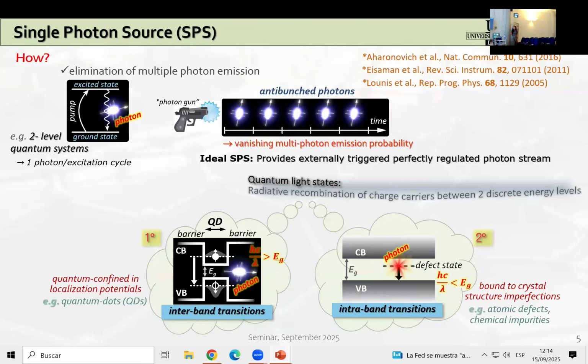Now, these systems can be made in such a way that the recombining charges are either quantum confined in localized potentials, like in quantum dots, for example, or they can be bound to imperfections within the crystal lattice. Like, for example, we are talking about atomic defects here or chemical impurities. So in both ways, per excitation cycle, there will be emission of a single photon, and the energy of this photon will depend on the system. So in this case, it will be above the band gap, and here it will be well below the band gap energy. So I will discuss both cases throughout this presentation.